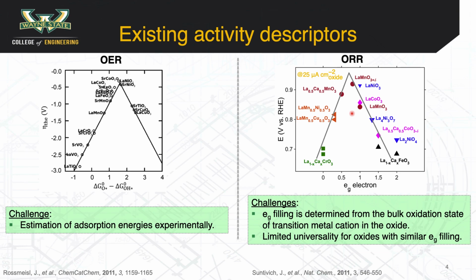Since catalysis is a surface phenomenon, there is a need to move towards identifying surface factors that determine the electrocatalytic activity. In addition, what is also interesting is that oxides with different B sites like manganese, nickel, and cobalt have been shown to have very similar eg filling, which also means they would have similar electrocatalytic activity, which may not be true, as I will show in the later part of my slides.